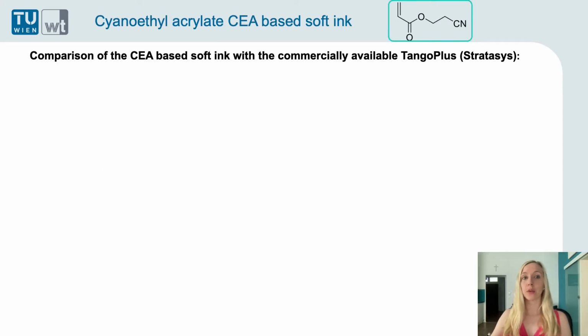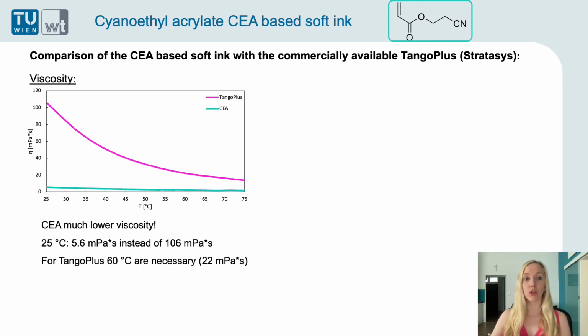So I developed a soft ink based on cyanoethyl acrylate with a low amount of crosslinker inside, and we wanted to compare it with the commercially available ink Tango Plus from Stratasys. So first I measured the viscosity, and you can see here that the cyanoethyl acrylate ink has a much lower viscosity than the Tango Plus.